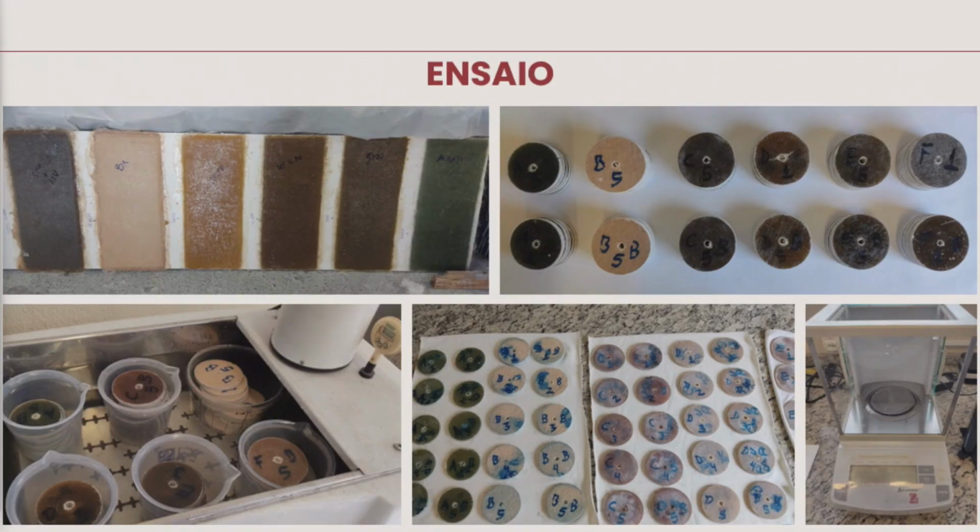Let us test whether this is true. The study that was carried out was this. We made a number of plates with 8 layers, all done on the same day at the same time to avoid the variable of temperature and weather conditions.